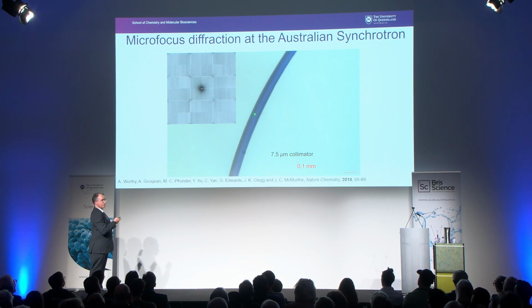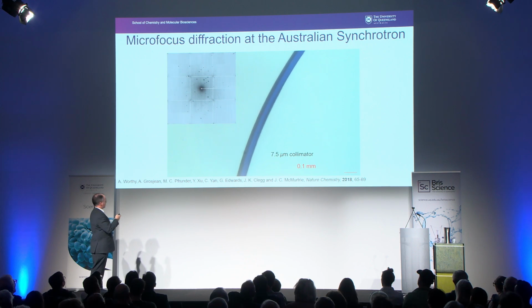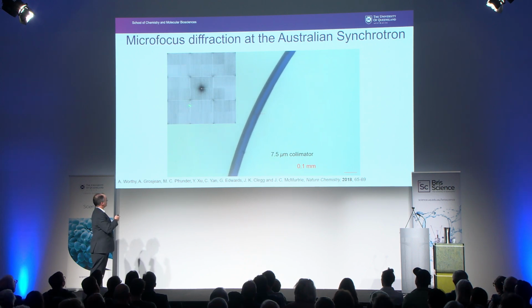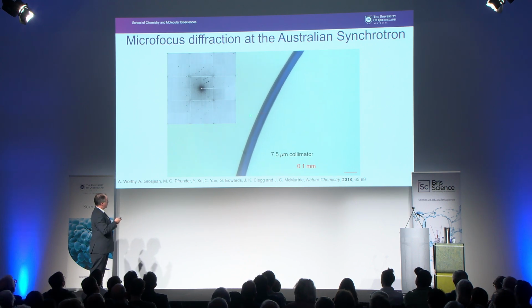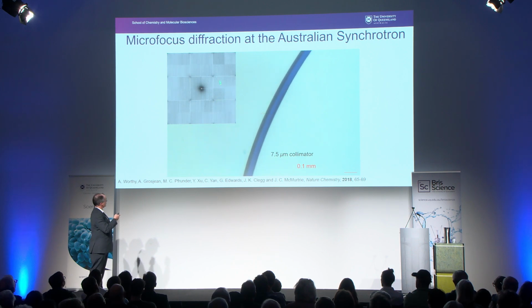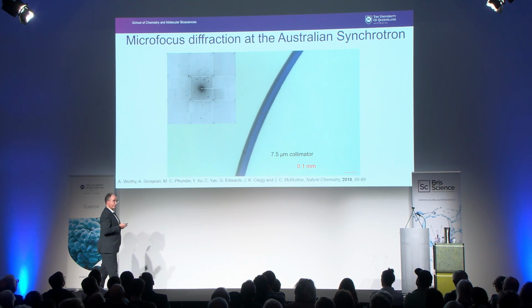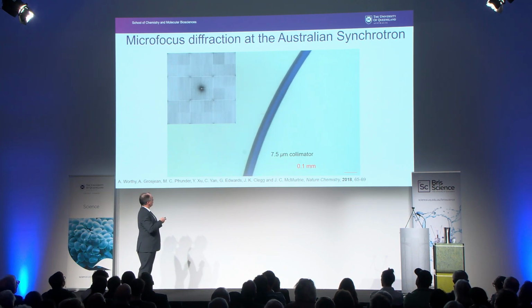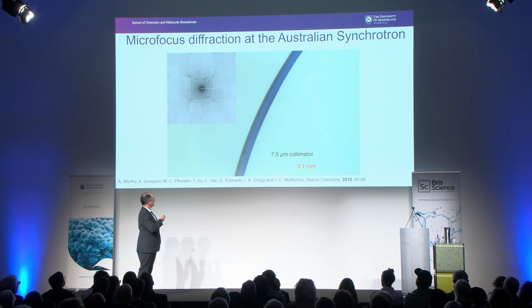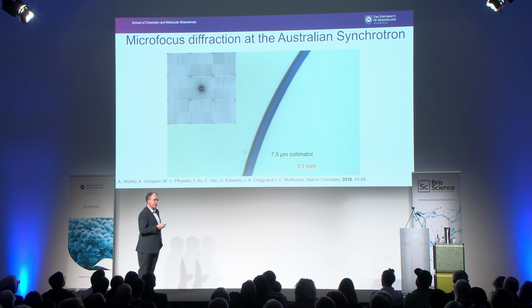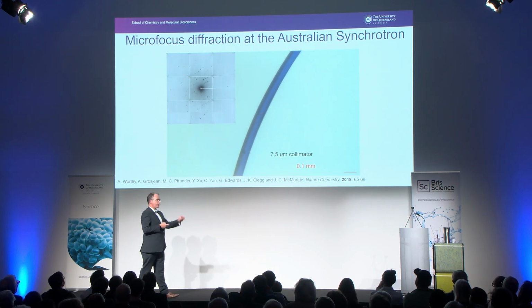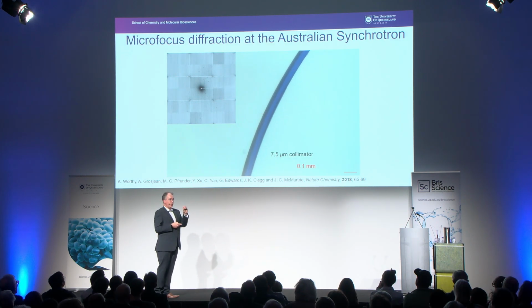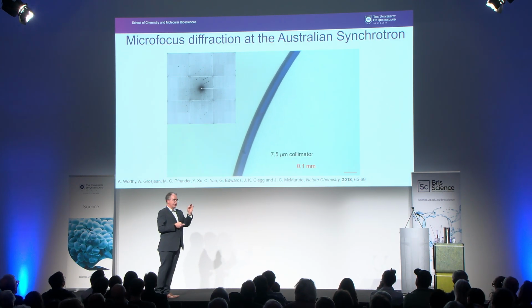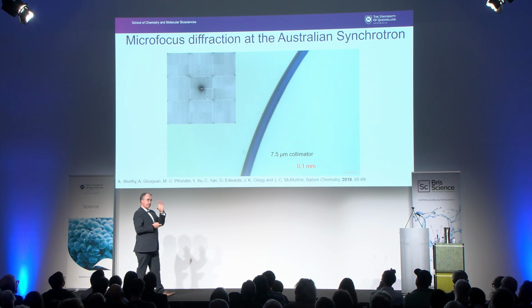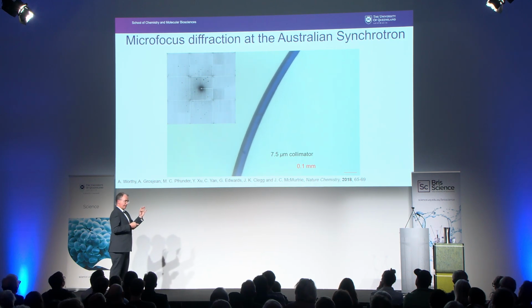And what we're doing is moving the crystal through the X-ray beam, and we're measuring the diffraction pattern as it comes through. We start on both sides, on the side of the crystal where there's no diffraction, and we move all the way through. And you'll see straight away with that smaller beam, even though this is in the bent part of the crystal, that those diffraction patterns are really sharp. And that means we're still seeing localized order in a very small sense that we don't see when we use a large X-ray beam.